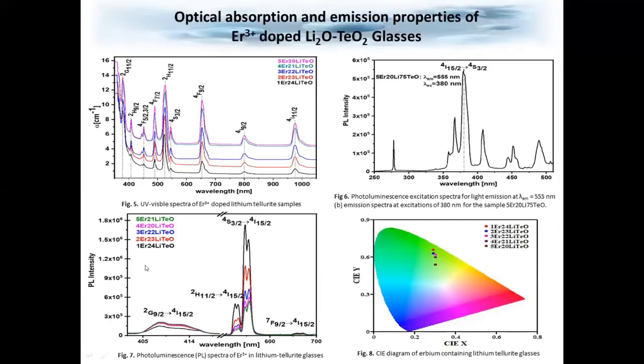And these are again the PL curves in figure 7. And you see as you increase the erbium oxide concentration, the PL intensity of light emitted around 500 nanometers decreases. So erbium doped samples, when they are excited with 350 nanometers, here we are using 380 nanometers, emit green light of wavelength 555 nanometers.